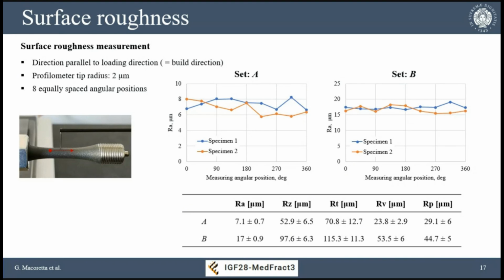Passing from set A to set B, the roughness more than doubles—increased by 140%. The surface roughness increased a lot in terms of average roughness, total roughness, and depth of the surface roughness values—a quite huge increase overall.